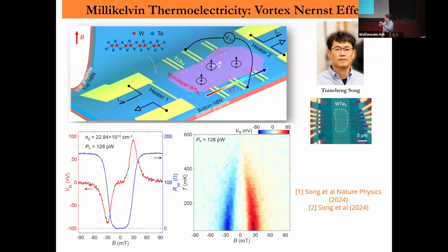In this case, it's because you apply current. If you measure resistance, you apply current, and the current will drive the vortex motion. That's why you have finite resistance, because you have finite current with finite voltage.